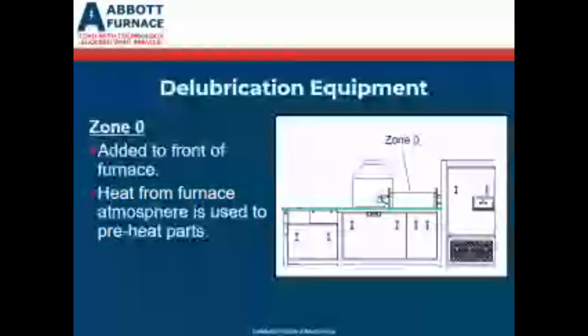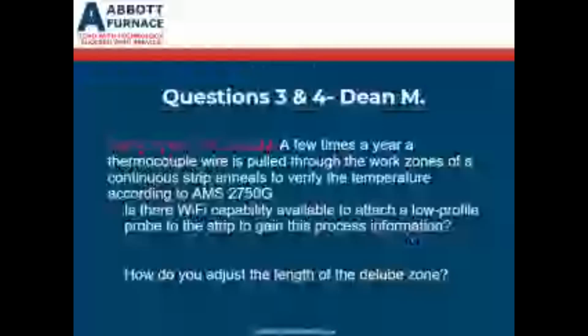The next one here, so it didn't transfer over, is just a plumbing schematic of what a bubbler or a picture of a QDP, how the muffle layout would be, to where we need to inject that at a lower temperature. If we get up above 1,400 degrees, then we run the risk of decarbing your product. So we put that up close in the first half of the preheat zone, where we'll inject that water vapor to raise that dew point to allow that reaction.